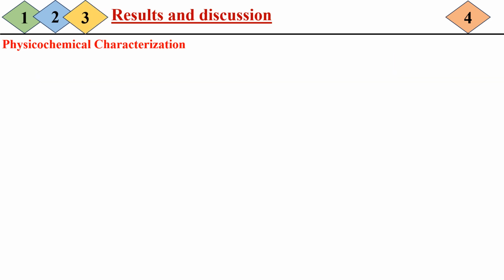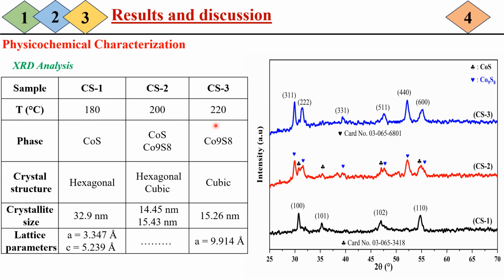So let's discuss our results. Firstly, our samples were characterized using X-ray diffraction. As you can see in the slide, the first sample is a cobalt sulfide phase CoS with a hexagonal structure. The second sample is a mixture of two phases, CoS and Co9S8, with hexagonal and cubic structures. And finally, the third sample, elaborated at 220 degrees C for 1 day, corresponds to Co9S8 with cubic structures. So, the X-ray diffraction confirmed the formation of cobalt sulfide nanomaterials.